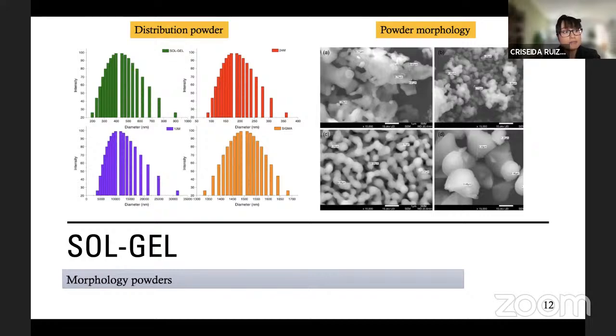The method permits us to understand that the milling time and the revolutions per minute are variables that directly affect the particles of the tricalcium phosphate. Furthermore, the field emission electron microscope shows that the sol-gel powders have spherical shapes, as you can see, whereas the mechanosynthesis powders, due to the grinding, generate agglomerates with irregular form.